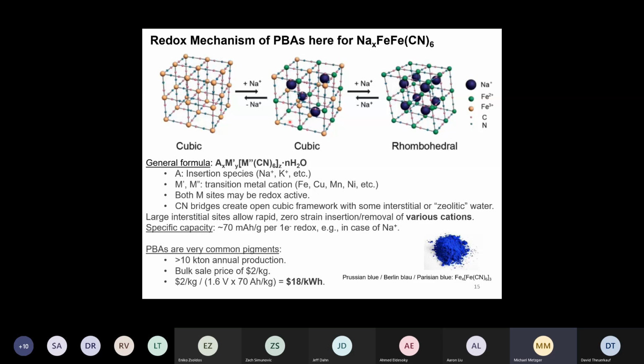To this middle stage, where so then it also sounds like a charge, potentially a charge issue then. So we recently did actually a study where we used this material. It was nickel hexacyanoferrate, and we wanted to intercalate this with sodium. Works beautifully, but if you add divalent ions like calcium, for example, to the structure, then you see a very rapid capacity fading.